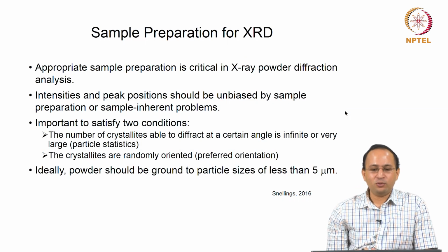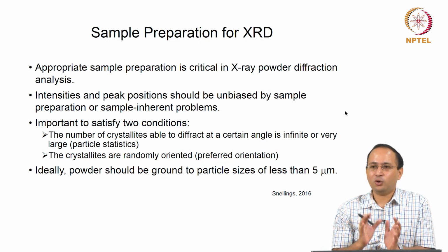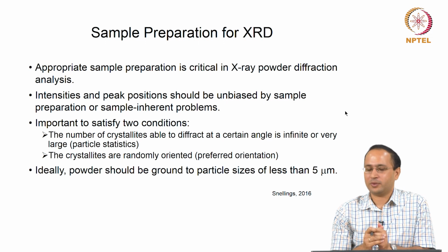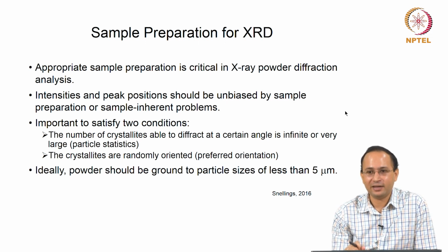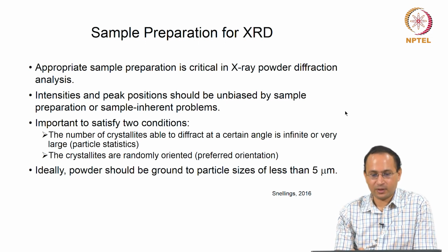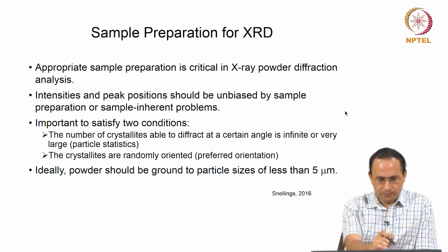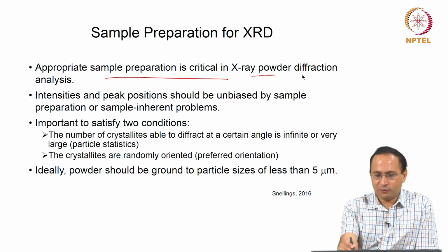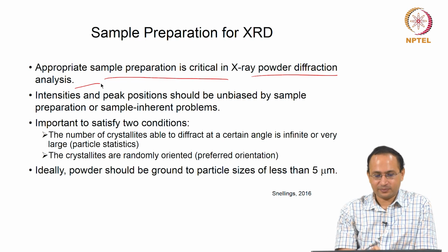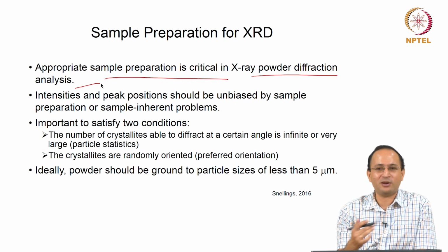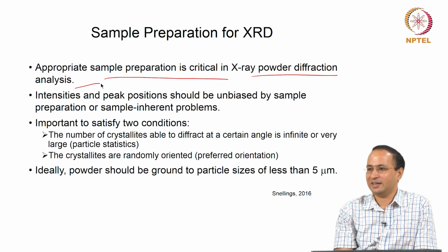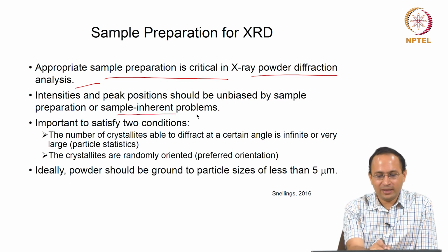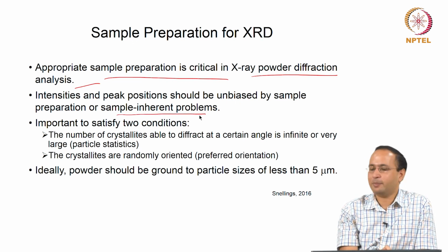Okay, now we will come to sample preparation for XRD. So, you got some general idea, right? How do we stop the hydration, and what other things, like grinding, can affect your properties. Appropriate sample preparation is critical for X-ray powder diffraction analysis. Intensity and peak position should be unbiased by sample preparation. You do not want to adopt a sample preparation which will affect your sample, right. So, it should be unbiased by sample preparation and sample inherent problems.